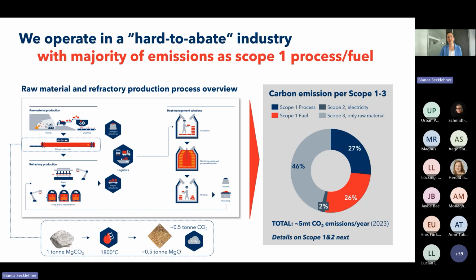And on the top, it is shown in more detail this calcination process, where if you burn a ton of MgCO3 at 1,800 degrees, you only get half a ton of MgO, which is the raw material for the refractory production, and half a ton of geogenic CO2 emissions. On top of that, there are also the fuel emissions, but basically these geogenic CO2 emissions are those hard to abate, which make us hard to abate.